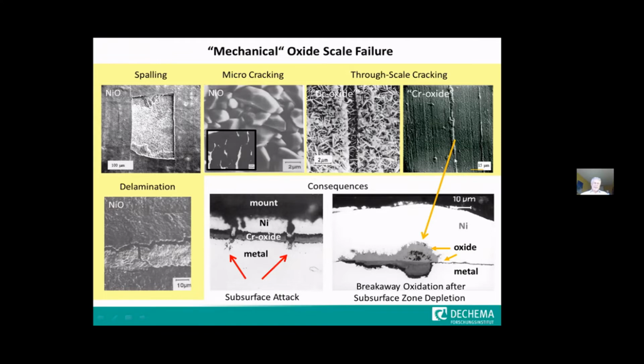I think we've heard it already in two talks before, at least in the first one, where an alumina layer was addressed underneath the TBC. This alumina layer is such a protective layer which keeps high temperature corrosive attack away from the substrate material. Such layers are the key to the performance under corrosive conditions at high temperatures. So we will have to look quite closely at such protective scales, even from a mechanical point of view. Later you can see what mechanical loads can do to these passive layers.